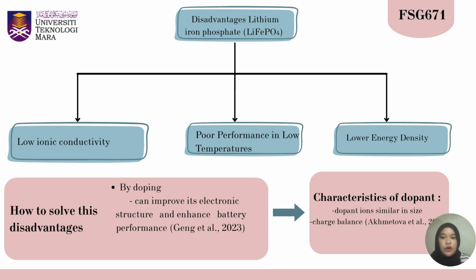While LiFePO4 offers many advantages, it is important to also consider its limitations. One major drawback is poor performance at low temperatures, which can affect battery efficiency in cold climates. It also has a lower energy density compared to other cathode materials, meaning it stores less energy per unit of weight. Additionally, LiFePO4 suffers from low ionic conductivity, which limits the speed of lithium-ion movement within the material.